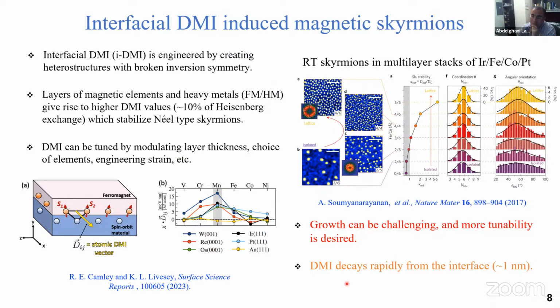Also, the DMI decreases rapidly from the interface. So if you go to a few nanometer thick ferromagnetic material, the DMI gets weaker. That's why you need many layers to increase DMI, and then you choose the heavy metal that has the highest spin orbit coupling.